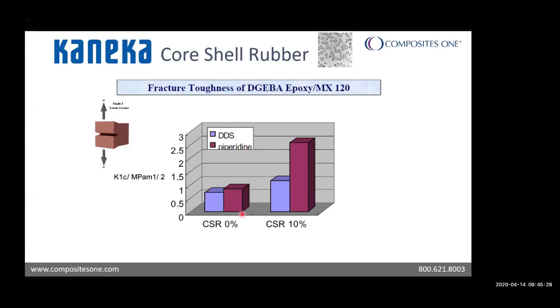So the bars here are at 0% loading, and then you can see at 10% loading how it improves the toughness, the K1C, depending on the type of hardener that you're utilizing. So another good toughness improver with very easy shear mixing into the resin system.